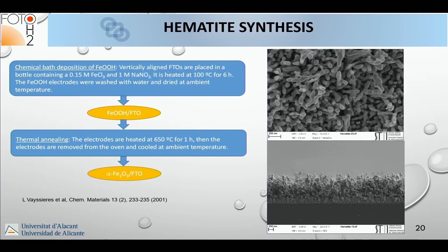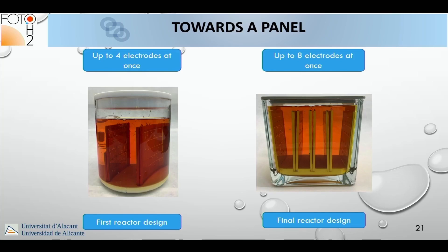As an example of hematite synthesis: we have nano-columns on the FTO substrate — the electrode is nanostructured, which is important for designing a proper photoelectrochemical cell. For scaling up to prepare enough electrodes for a prototype or demonstrator, we used chemical bath deposition, which is very easy to scale up, and refined it to maximize efficiency.